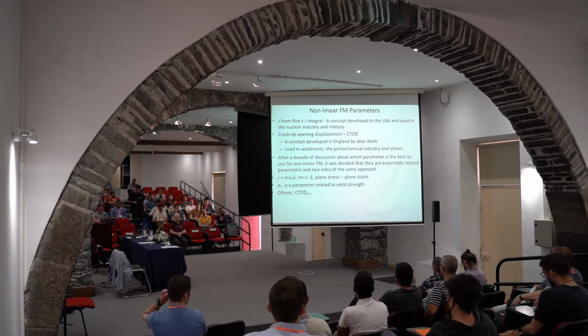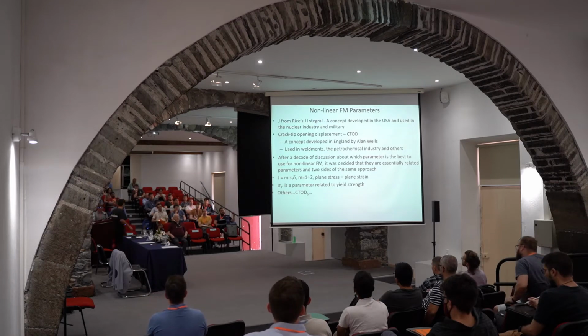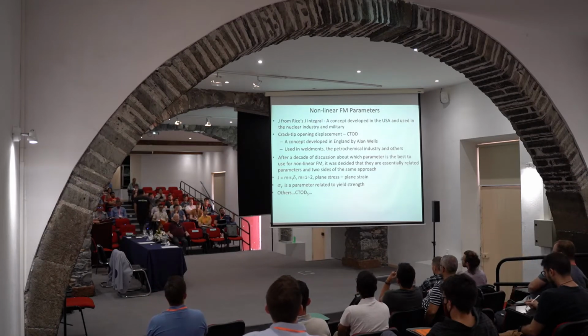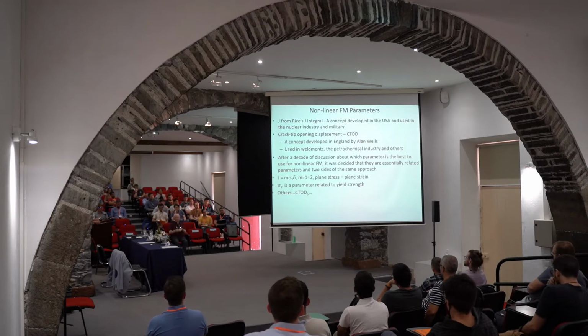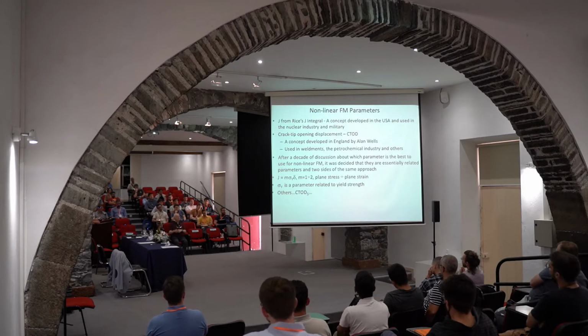There was a strong discussion for decades that followed after the 60s, about which parameter is better and so on. But the final decision, in a way, is that they are about the two sides of the same approach, and they were later on related, correlated, although not with an exact equation. You can see that there is a coefficient m which depends on plane stress versus plane strain conditions, so it's not exactly from continuum mechanics, but a bit more empirical.